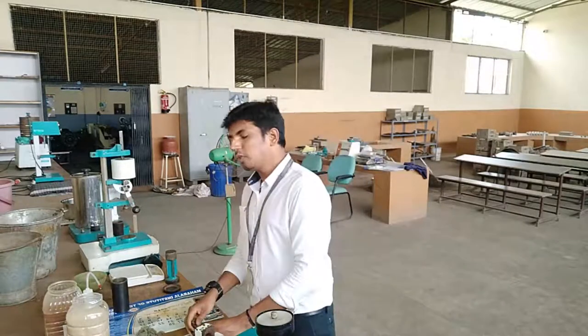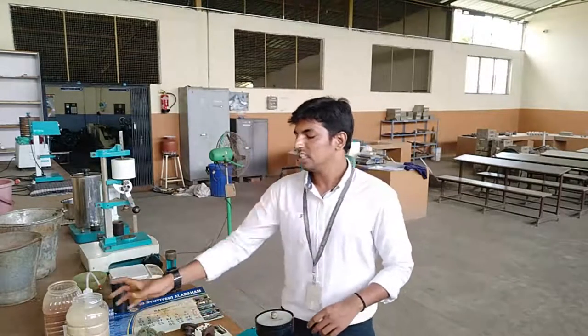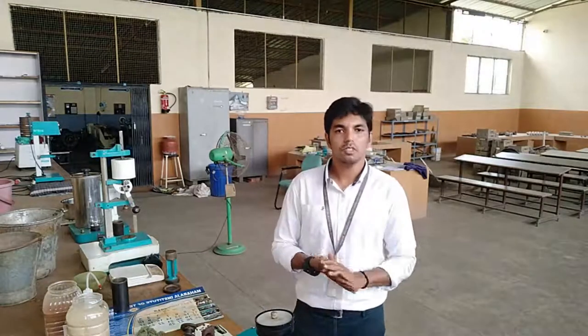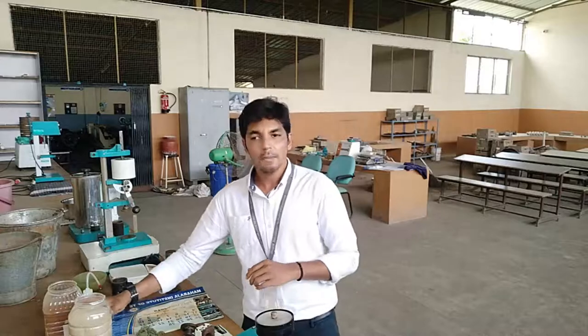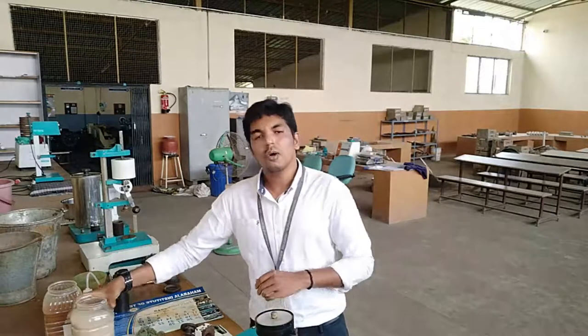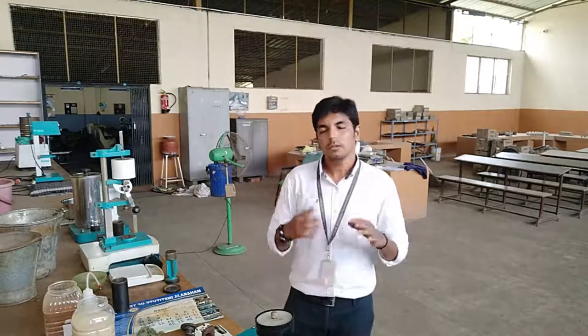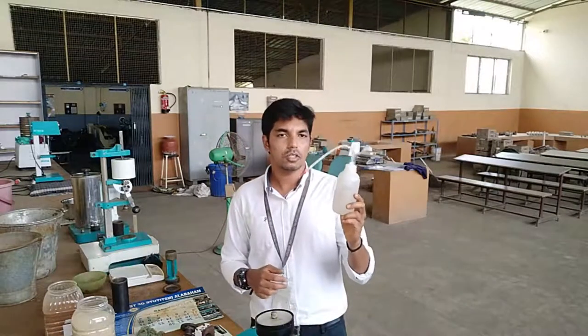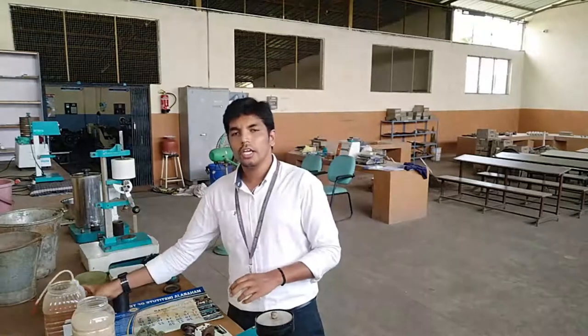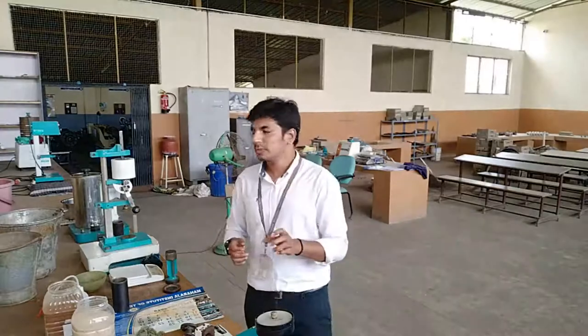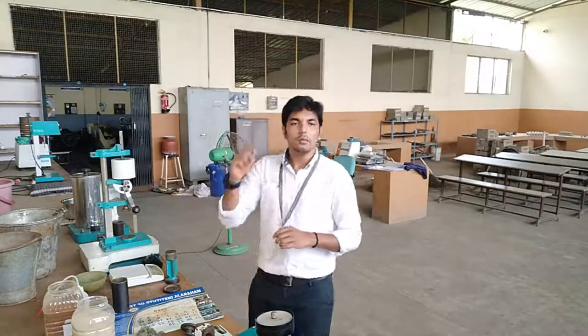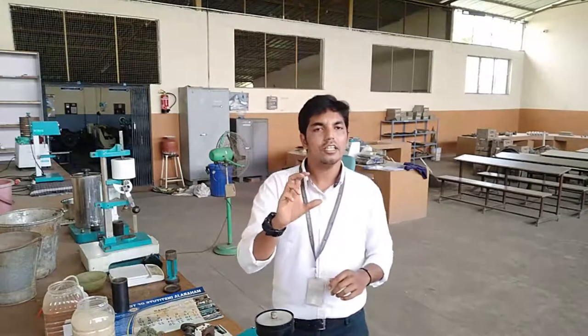So how do we prepare the sand testing specimen? Here the sand specimen is prepared for 150 grams. For 150 grams, I am taking 10% of clay. 10% of clay means 15 grams of clay and then 135 grams of silica sand to match the total 150 grams of molding sand. Then I am adding 8% of water, that means 12 ml of water. After that, take the sand into this sand rammer and apply the ramming force in order to create the sand specimen.